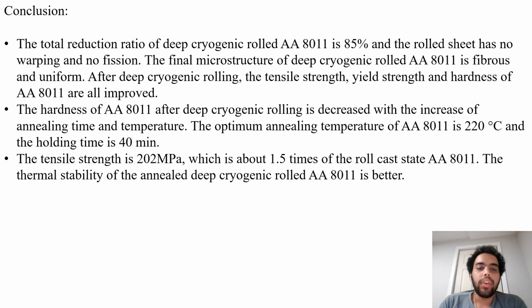Conclusion: the total reduction ratio of deep cryogenic rolled aluminum is 85%, and the rolled sheet has no warping and no fission. The final microstructure of deep cryogenic rolled aluminum 8011 is fibrous and uniform. After deep cryogenic rolling, the tensile strength, yield strength, and hardness of aluminum were all improved. The hardness of aluminum after deep cryogenic rolling decreases with the increase of annealing time and temperature. So hardness has an inverse relationship with annealing temperature. The optimum annealing temperature for aluminum is 220 degrees Celsius and the holding time is 40 minutes. The tensile strength is 202 megapascals, which is about 1.5 times that of AA8011. The thermal stability of deep cryogenic rolled aluminum is better.